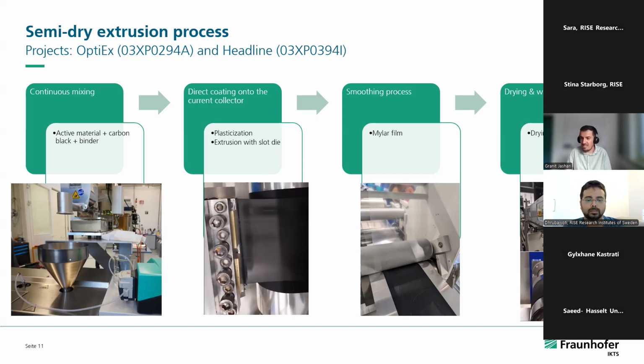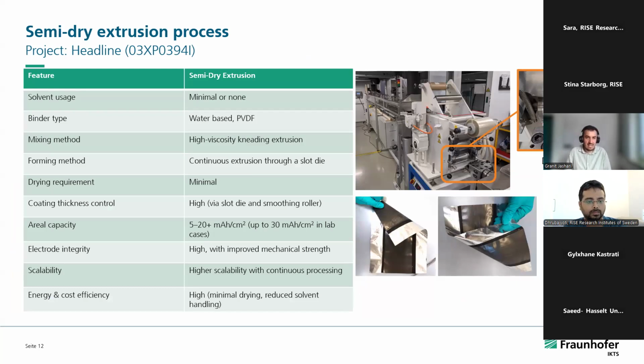And the last step is where we do the drying, and then the winding, and then we do the calendaring of the electrodes. Here we are just highlighting some features from the semi-dry extrusion. As I mentioned, the solvent is really minimal. The binder, as I said, we could use different binder systems, water-based, PVDF, so we are not limited on the binder.